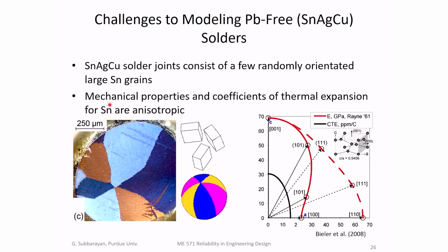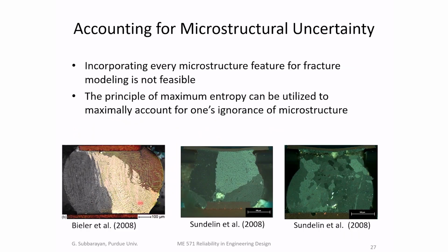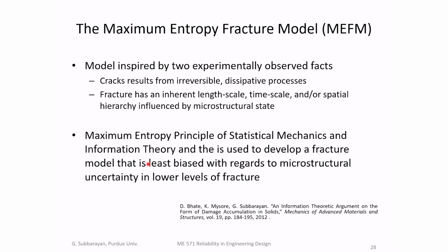And later, we were characterizing tin silver copper solder alloys, and it turns out tin silver copper solder alloys have very few grains in them. If you take a cross section in a solder joint, you'll find very few grains in them because tin tends to grow, and it's primarily tin. There are very few tin grains in a solder joint because of what's called tin undercooling. So there's a fair amount of microstructural uncertainty because of the fact that there are very few grains in these tin-based solder joints.